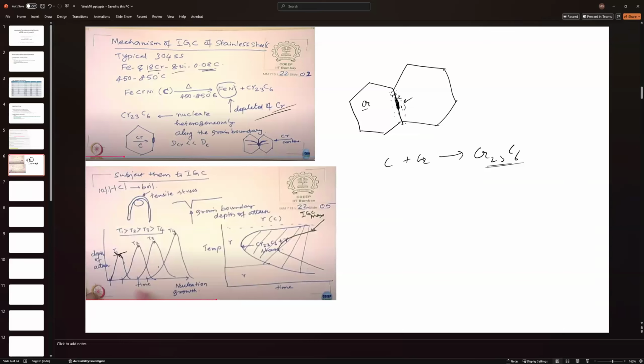Now chromium from the bulk is diffusing toward those precipitates areas, again stabilizing them. So after a time, the depth of attack stabilizes, but the corrosion has already happened, and you'll see in the microstructures corrosion happening around the precipitates.